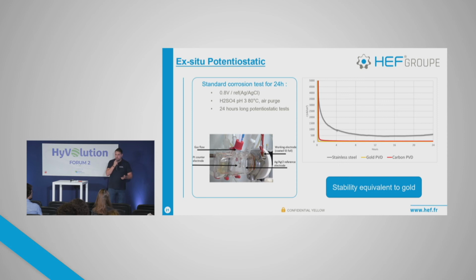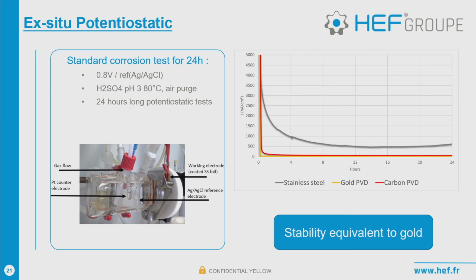The second point, what is really, really important, is the corrosion of your layer. Gold is the best solution. Why? Because it cannot react in the environment of the fuel cell. It's thermodynamically stable. So the aim was to find the good carbon composition which has the lowest reactivity in the environment, and this is what we did. In fact, the reactivity of the carbon we have developed is so low that you have the impression it's gold. So you have a really, really long durability, higher than 10,000 hours in the latest test we have performed.